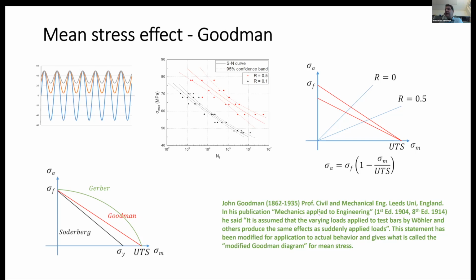And he suggested that there is a relationship between sigma alpha and sigma m. Sigma alpha, you remember, was the amplitude, and sigma m the mean stress, and also the strength of the material. He suggested a linear relation between these. So this means that we can interpolate between known R ratios and estimate the lifetime of a material at a different R ratio, a different condition. This was introduced in 1904, so 100 years ago. Today we know that it does not work well for composites. It is still working well for metals.